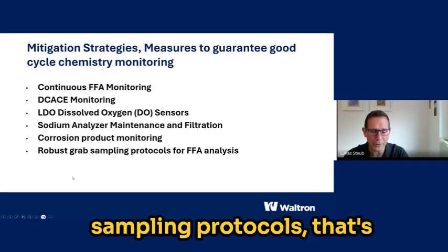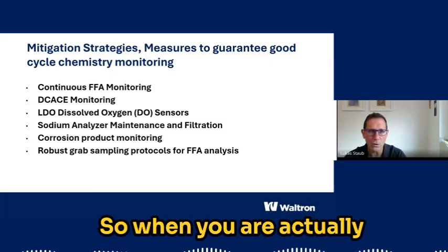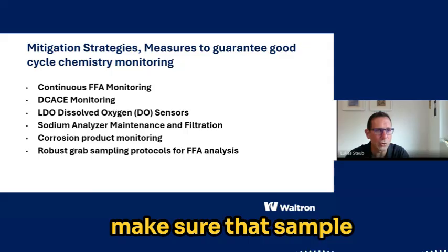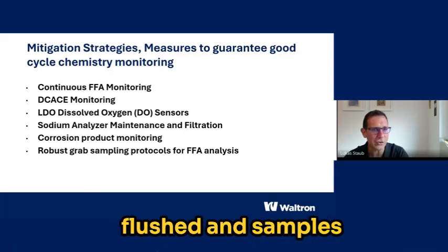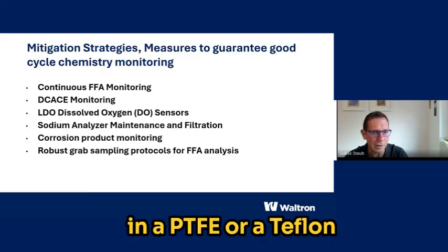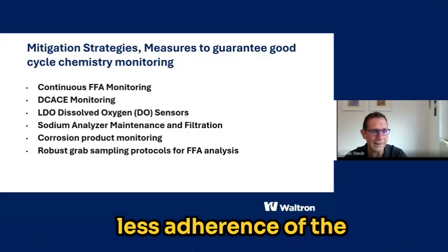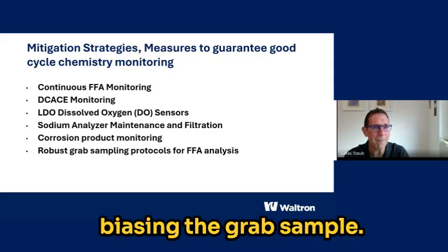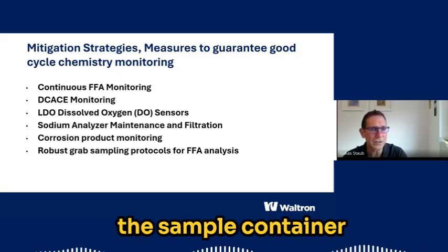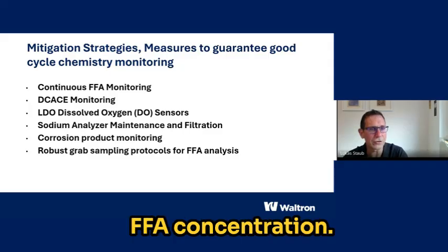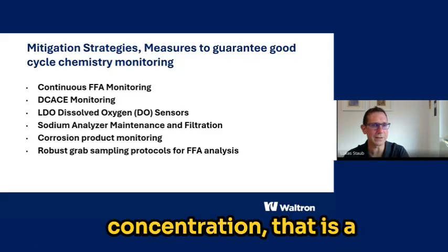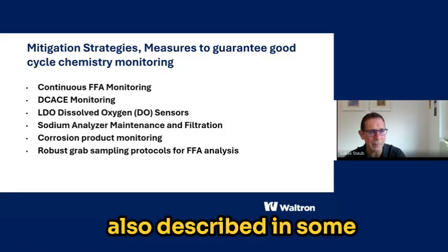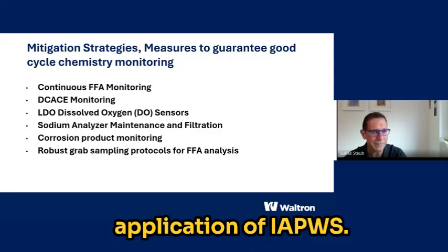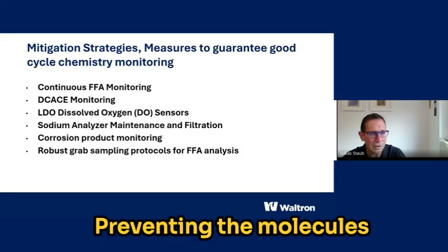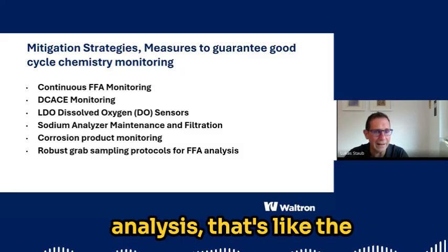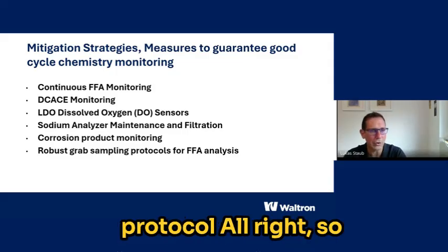And the robust grab sampling protocols, that's one of the things that I just mentioned before. So when you are actually doing grab sampling, make sure that sample lines are thoroughly flushed and samples should be captured in a PTFE or a Teflon or silicone-coated container, which has less adherence of the FFAs, so therefore not biasing the grab sample. Adding acetic acid to the sample container will adjust the pH and stabilize the FFA concentration. So if you want to actually grab sample for the FFA concentration, that is a procedure that has also been described in some of the guidelines of FFA application of IAPWS. EPRI has a similar guideline for that, preventing molecules from absorbing to the walls prior to the analysis. That's like the goal of that grab sampling protocol.